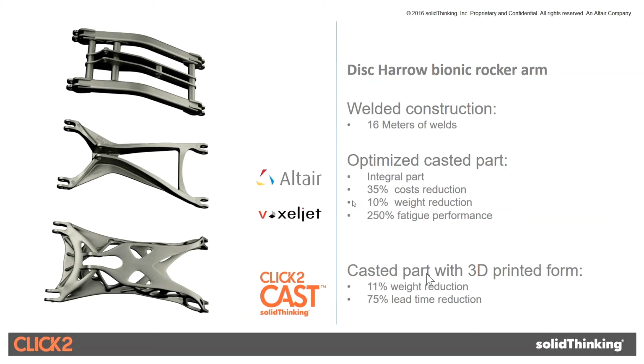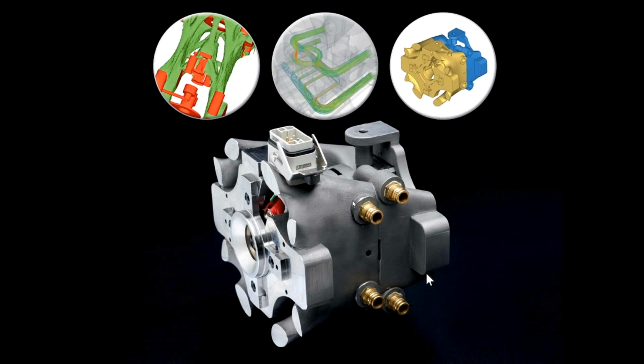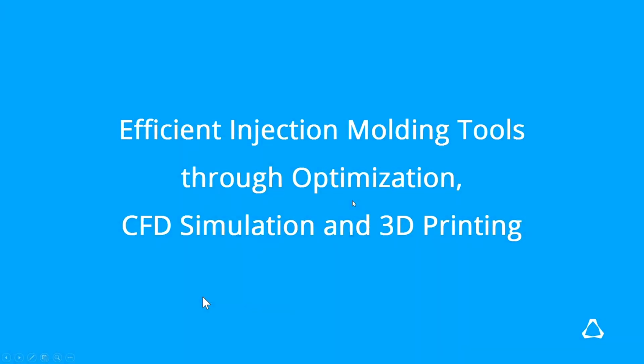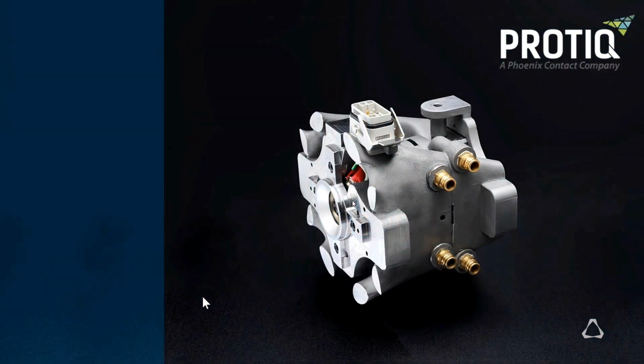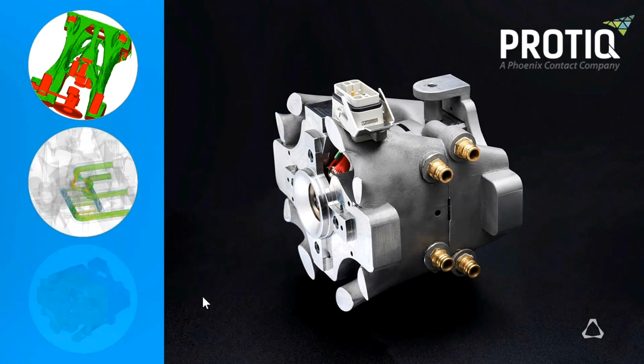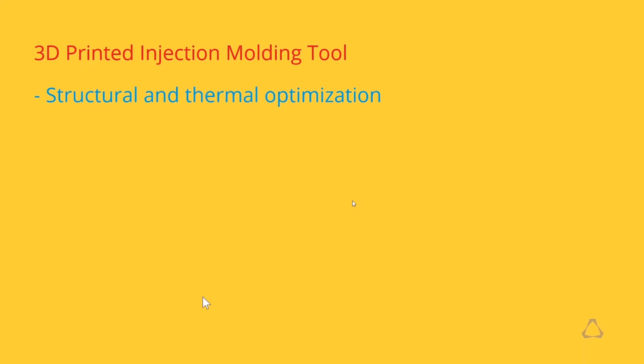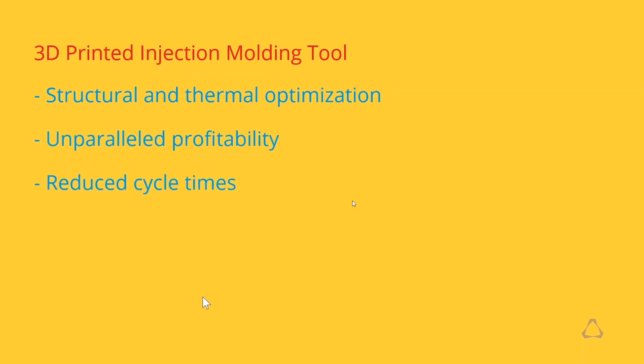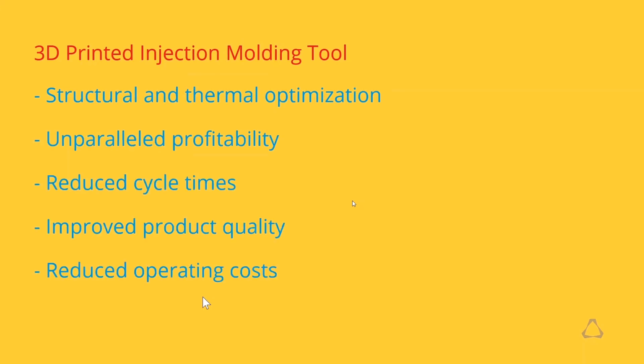I want to also take another example, and here in this case, I'm moving from a sand printed mold to a 3D printed die for an injection molding die. Okay, so in this case, what did we do? It was a very interesting case as well. We worked with Protiq on this in Germany, and 2 things. This structure that you see on the right hand side was optimized both for structure as well as thermal optimization. So it was structurally optimized and thermally optimized, and we'll see that in a second.